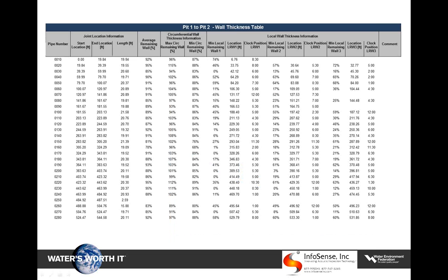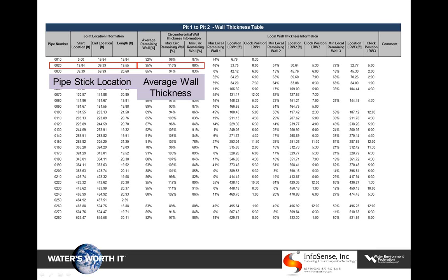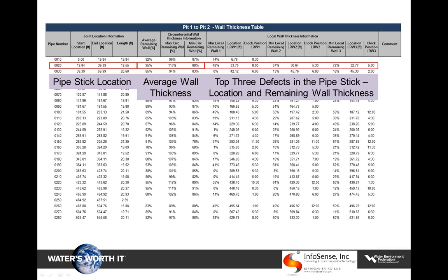This is a large table. This is actually one small part of the data that we got from the Sea Snake for this line. And I wanted to show this table for a couple of reasons. One, each row is a distinct, discrete stick of pipe. In other words, the first 4 columns indicate the number of the pipe and where the pipe is located. It actually identifies each joint of pipe. The next 4 give you average wall thickness as a percent of a calibrated nominal wall. And what's really of value to us, these 9 columns give you the data on the top 3 defects in each pipe stick. The location along the axis, the clock location, and the percent remaining wall thickness. Very good data.